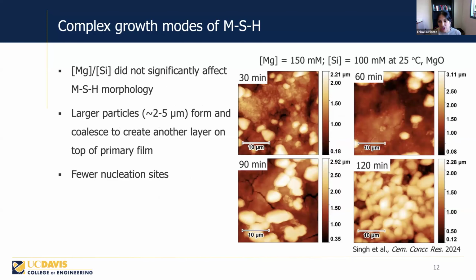And then we can watch this reaction happen over time. This is 30 minutes, 60 minutes, 90 minutes, 120 minutes of reaction. We can see that this is the layer that we observed from the 15-minute reaction from the previous slide, is composed of these nanoparticles.